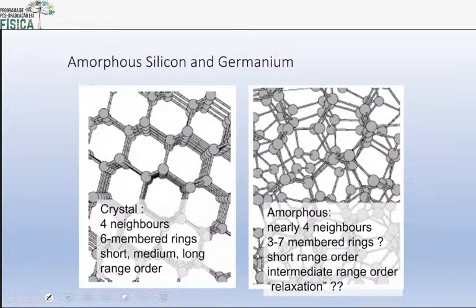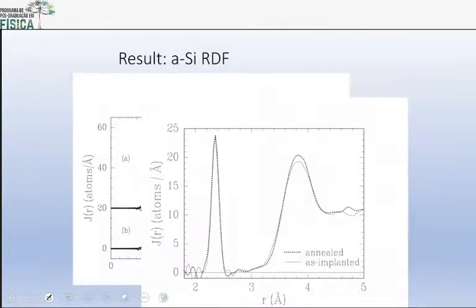So I'm going to show you very quickly some very initial work that we did, where I'm going to go very fast here because there's a lot of stuff to cover. So we first looked at some amorphous silicon, and amorphous silicon is an interesting material that, well, it's amorphous. It's not crystalline, so it has no Bragg peaks, but we Fourier transformed the pattern, okay? And we get a nearest neighbor, and that's the nearest neighbor. And that's the next nearest neighbor.